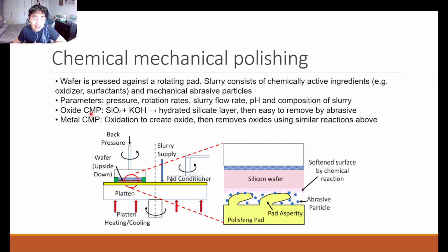Whereas for metal CMP, normally we add certain oxidizing agents in the slurry that oxidize the metal to create the oxide, and the oxide layer can then be removed by a high pH solution by forming certain hydroxide complexes with the metal that can be more easily removed, for example.